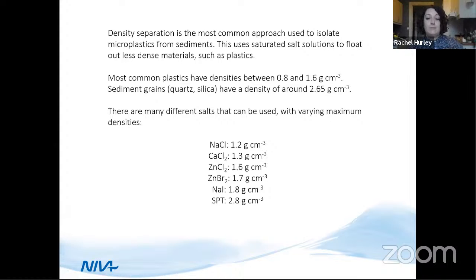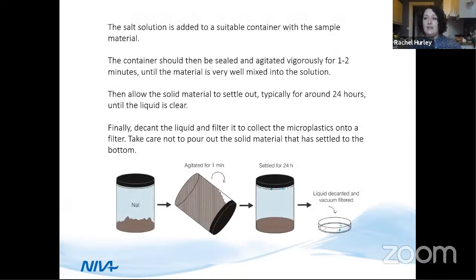You can use obviously cheaper and more accessible solutions such as sodium chloride, but you must consider that this won't extract the full range of potential microplastic particles, because the 1.2 grams per cubic centimetre doesn't cover the full range of plastic types. So you may not actually be extracting everything with that. So there's a trade-off to think about when you're selecting the density solution. To undertake density separation, the salt solution should be added to a suitable container along with the sample. Remember to pre-filter the solution before you use it each time, as it may contain some microplastic contamination.